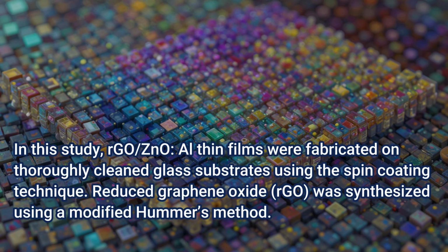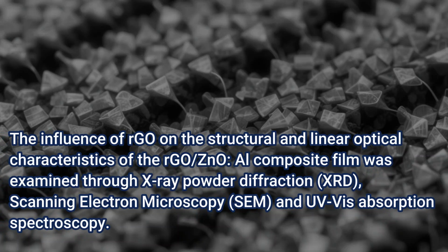In this study, rGO AZO thin films were fabricated on thoroughly cleaned glass substrates using the spin coating technique. Reduced graphene oxide, rGO, was synthesized using a modified Hummers' method. The influence of rGO on the structural and linear optical characteristics of the rGO AZO composite film was examined through X-ray powder diffraction, XRD, scanning electron microscopy, SEM, and UV-vis absorption spectroscopy.